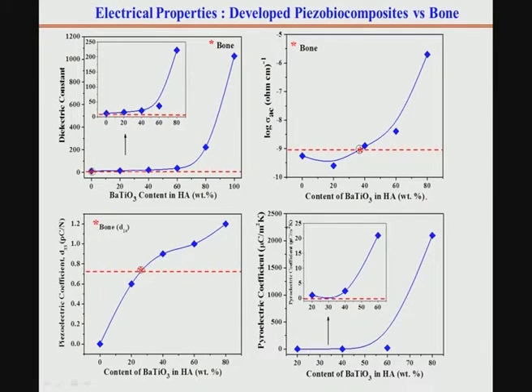Now, all these functional properties that we have measured include dielectric constant, electrical conductivity, piezoelectric strength like d33 values, and pyroelectric coefficient. What we have observed here is that depending on the barium titanate content in the hydroxyapatite matrix, this piezoelectric strain coefficient can go up to 0.7 values, and this 0.7 is close to that of the 30% barium titanate. We have got a few compositions, 20%, 40%, 60%, and this 0.7 piezoelectric strain coefficient is somewhere in the